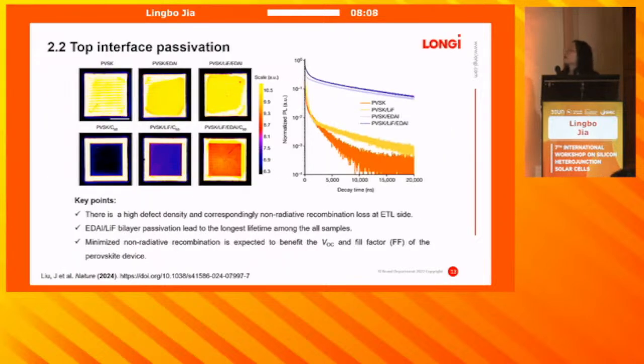Apart from the bulk passivation, we have also focused on the top interface passivation. From the PL mapping measurement, we can notice that the bulk perovskite films without any capping layer exhibit the higher PL intensity. But when we directly deposit carbon-60 on the perovskite surface, the PL intensity and also the lifetime decreased very fast. So we suppose that there is a high defect density and corresponding non-radiative recombination loss at this side.